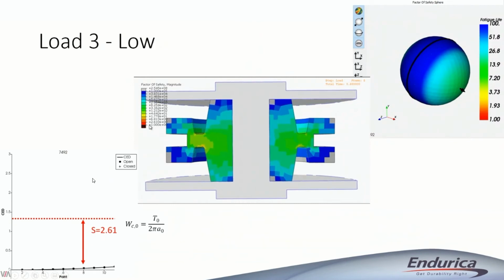The color red is a safety factor of 1. So if you see red, that means that basically you're right on the line. Anything colder than red is a safety factor that's bigger than 1. And in this case, the worst safety factor is in this corner. You can see it's just a little bit orange, maybe. And if you click on that and open it up, you can find out the safety factor in that worst case is about 2.6. So this tells us that we have a margin of about 2.6 on the crack driving force. So we would say this is safe. We could expect infinite life, like I say, for the moment ignoring aging. Aging can change the threshold, so you do have to think about that. But anyhow, that's the small load case.